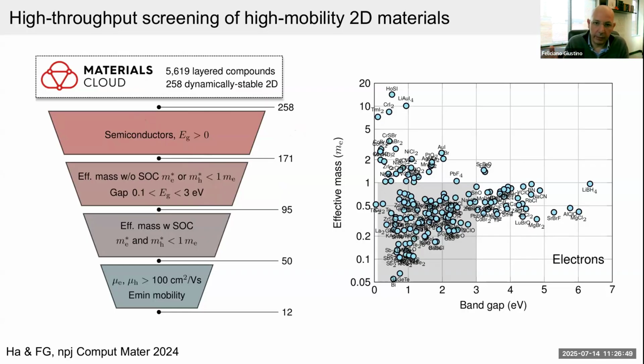And then you perform a little bit more advanced calculations, and you keep narrowing down. And when you reach the bottom tier, you're doing your most advanced calculations for maybe a dozen, 10 to 20 compounds. And just to give you a sense of the complexity, a calculation of carrier mobility at the highest level today is not something that you can do on a desktop in a few minutes. This is something that usually requires high performance computing, and maybe one calculation will require 1 or 2 weeks of supercomputing time.